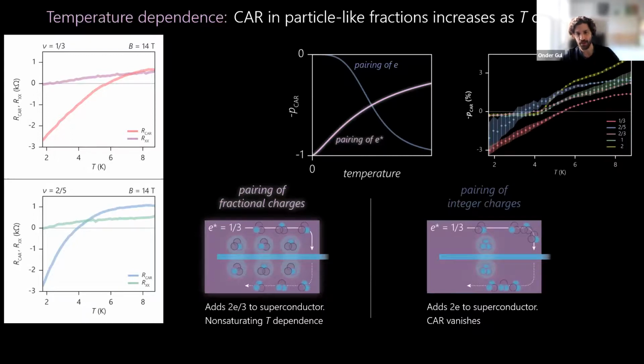Comparing this temperature dependence of particle-like fractions to the integers and hole-like fractions highlights the differences. Integer and hole-like fillings have a small but non-zero CAR, which saturates at low temperatures, different from the particle-like fractional fillings. This saturating temperature dependence is, however, noteworthy in itself, because the very low CAR probability suggests decoherence processes as the dominant suppression mechanism. But below 4 Kelvin, there is no strong temperature dependence. So this is an open question.